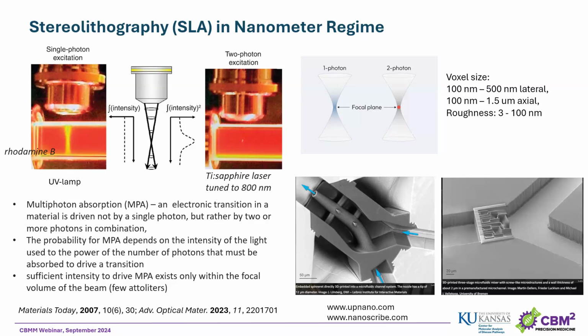And this gives this tremendous resolution that you can get with stereolithography. As you can see, the voxel size can go down to 100 to 500 nanometers laterally. It's a little bit bigger in the z-axis, at 100 nanometers to 1.5 micrometers, and you can achieve really low roughness.